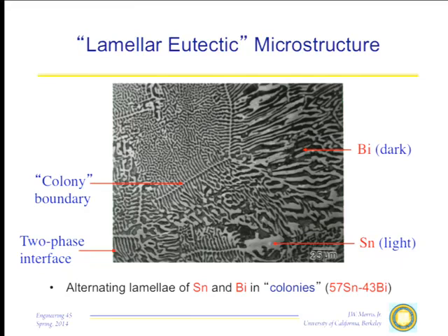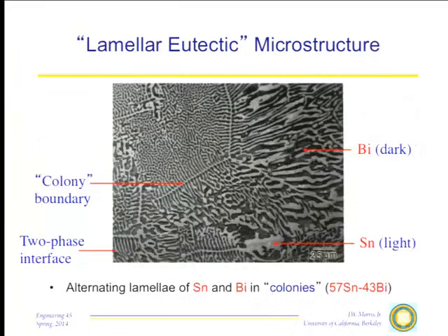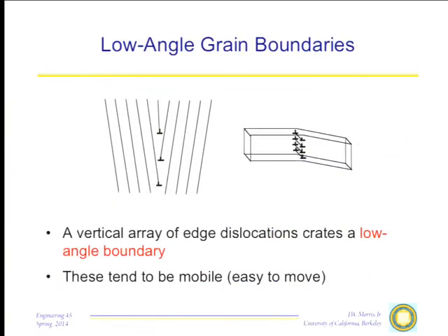And depending on how you make the microstructure look, you can influence and control the properties. Bismuth-tin like this actually has rather poor mechanical properties. If I just reprocess the bismuth-tin so it looks like this, it becomes what's called a superplastic material. You can stretch it like bubble gum, and it will hardly break. Whereas in this microstructure right here, mechanical behavior is rather poor. So the grain configuration makes a very, very big difference in what the properties are going to be.